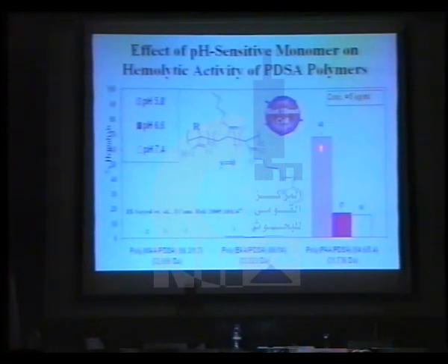But by the time with this composition you're down at pH 5.8, this polymer is converted into a membrane destabilizing form. And we've done a lot of work. You can very nicely tune exactly what pH this occurs. We have polymer compositions that will destabilize at pH 6.6, for example, and not at 7.4. So these are activated extremely sharply, very similar to the biological proteins, across a pH range of less than half a pH unit, and it's fully reversible.